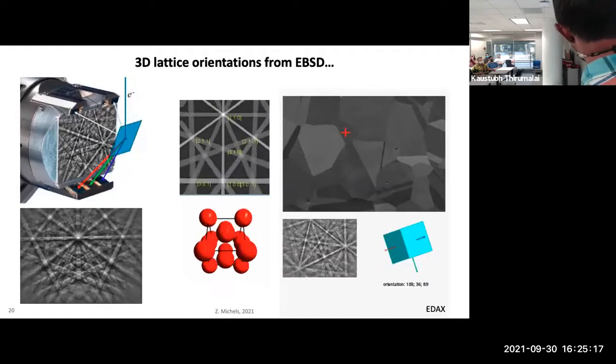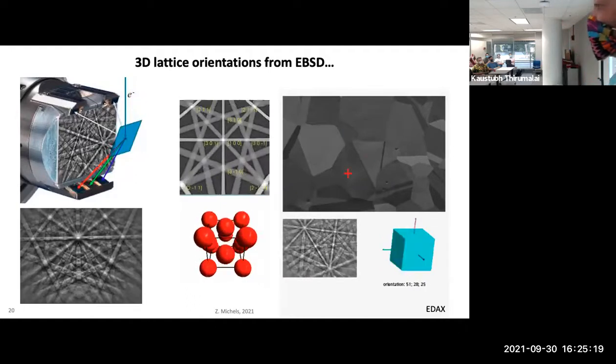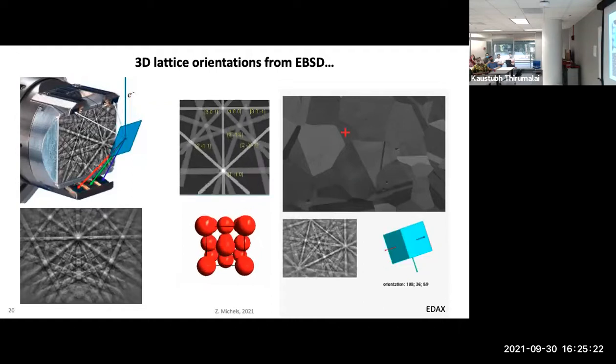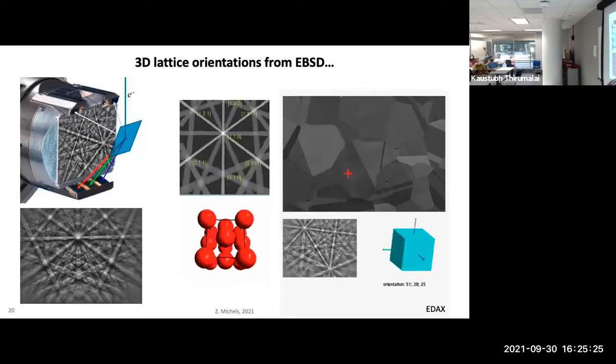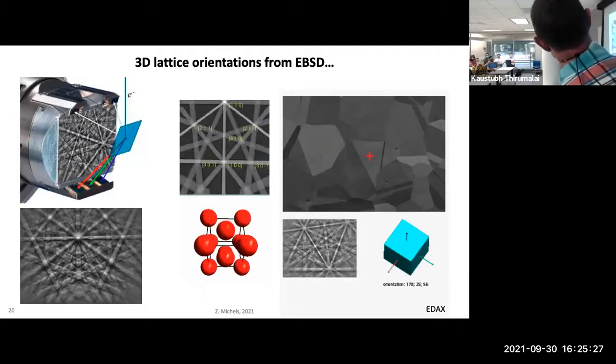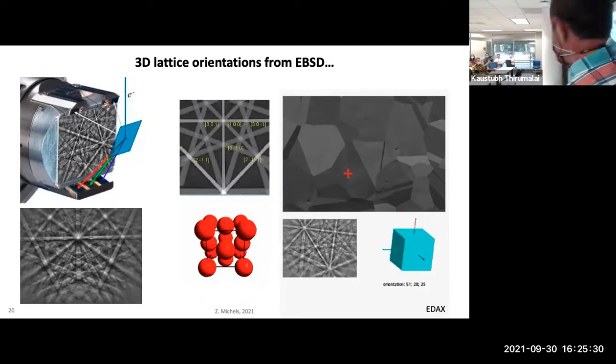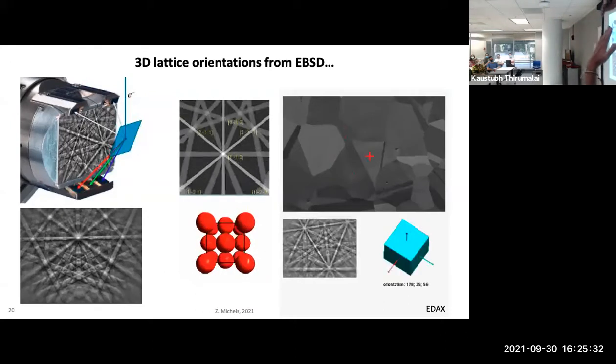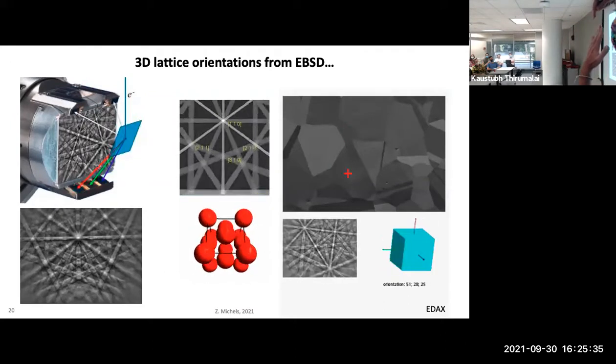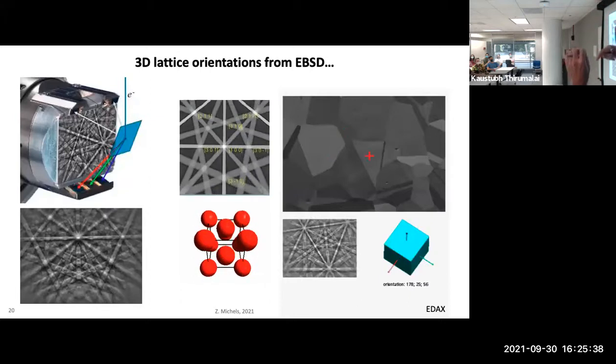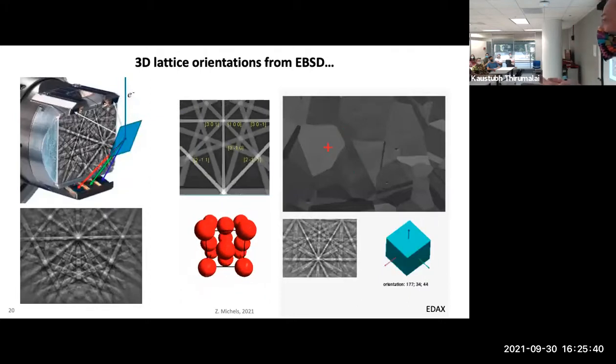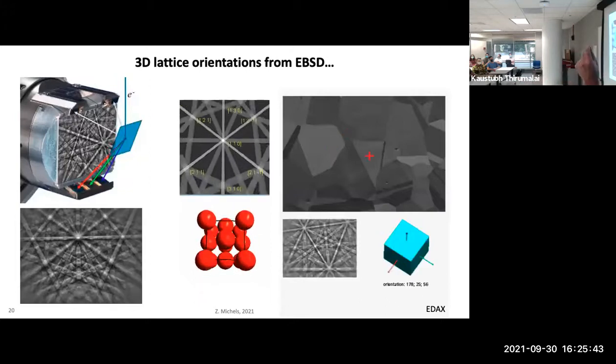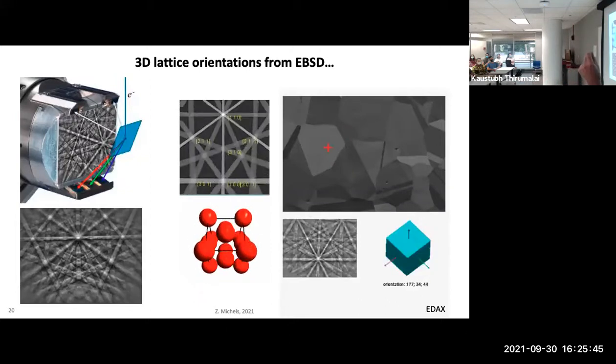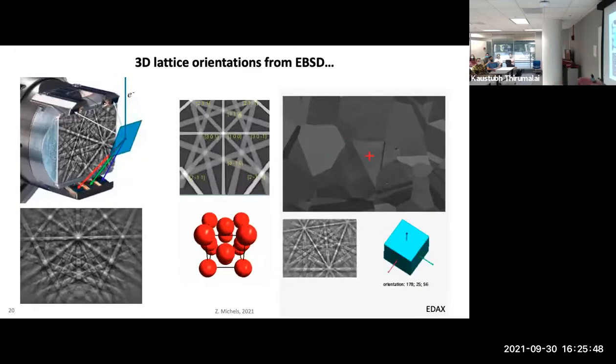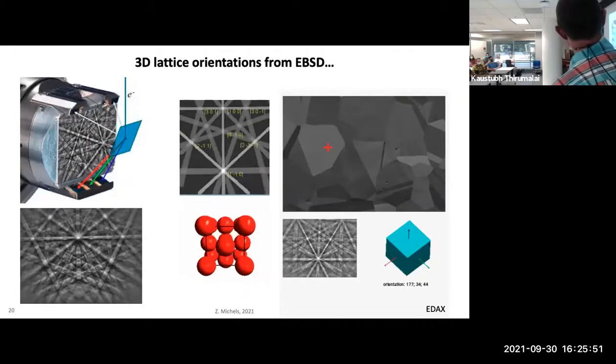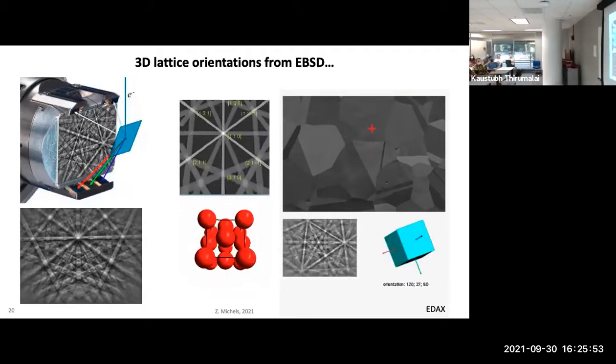What we ultimately get are these pictures like you see down in the lower left, which are beautiful. These are called Kikuchi patterns. What you're seeing is there's a phosphor screen, like is shown up here in the left. And we have to tilt the sample at a really high angle to the incident beam. And what that allows to happen is the electron hits the sample and channels along the lattice planes in only the uppermost couple angstroms of the material. So it has to be crystalline for this to work because it channels along the lattice planes, and then it flies out in sort of a ball of electrons that come channeling out of the surface.